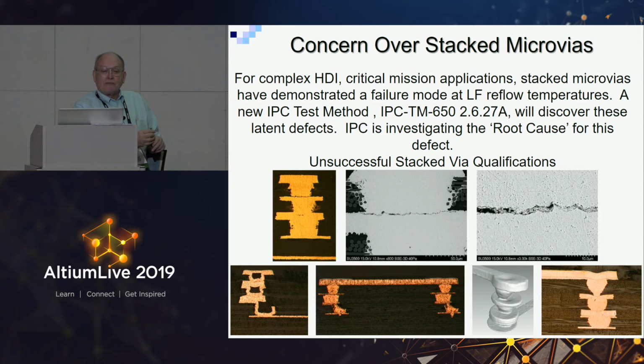We're having a new problem on military and space, in that anything over 2 levels stacked vertically is failing in space or failing in the field. So we have a new test method, 2.6.27a, that is effective at discovering these latent defects. And we're still investigating the root cause. But right now, we published in the IPC a warning: do not stack vias on mission critical products more than 2. So if any of you are mission critical and you've got more than 2 stacks, immediately go back and change the design to only 2.